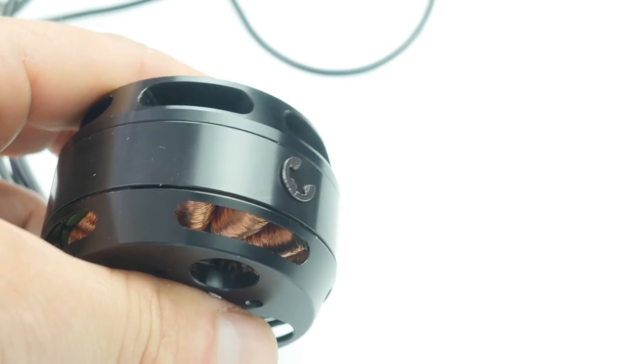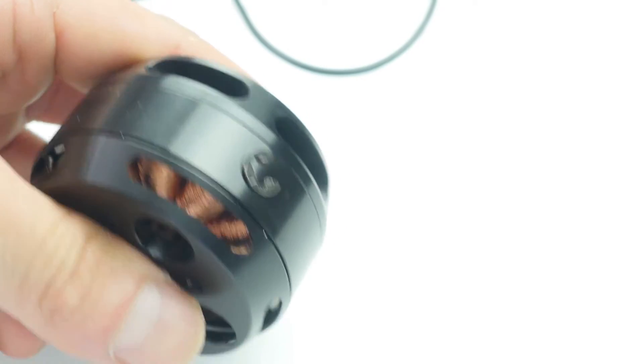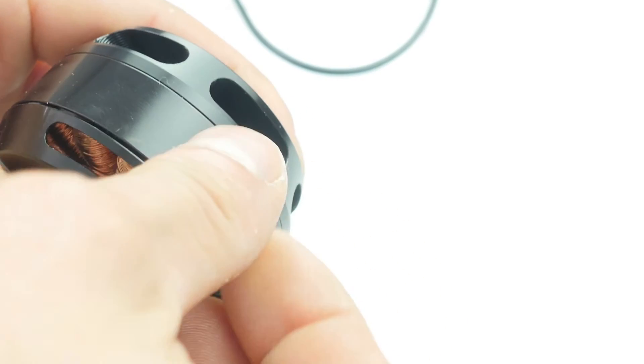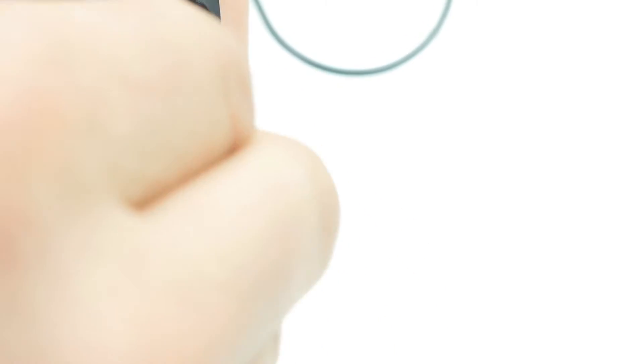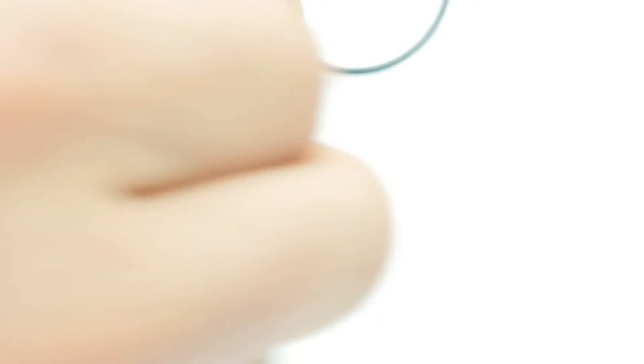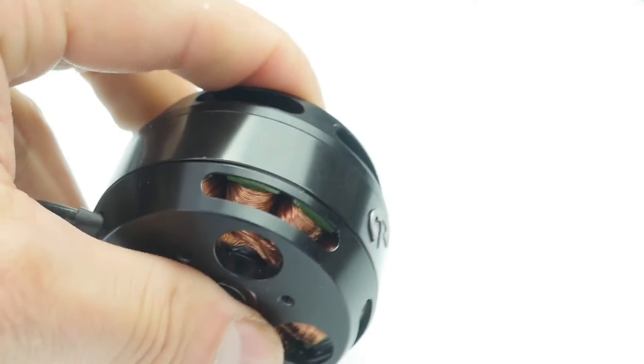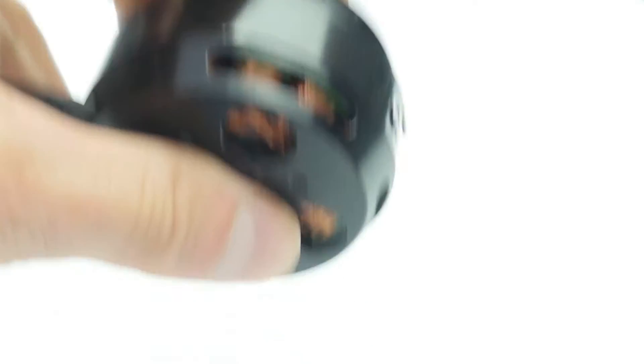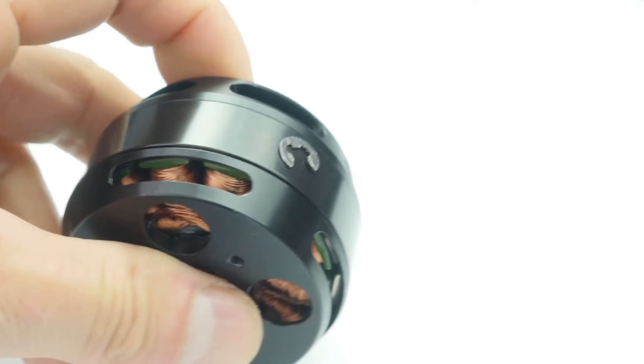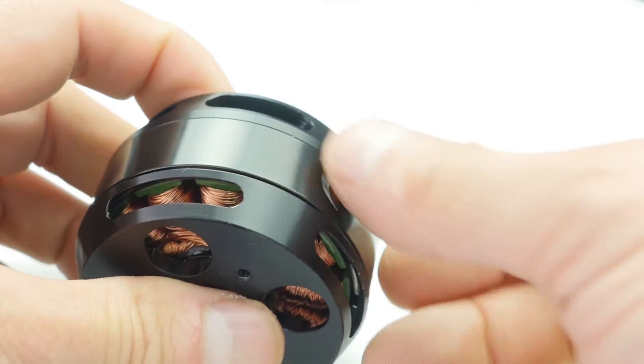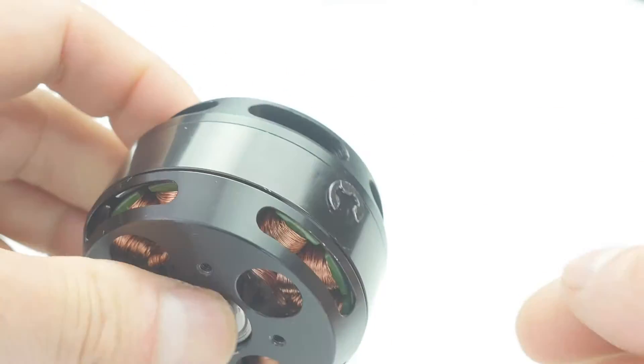The way in which the blue balancing epoxy is applied definitely leaves a lot to be desired. Magnetism that's lost through the outside of the end bell is called flux loss. This steel E-clip, which shouldn't stick at all, shows how much magnetism is lost through the outside of the U7. The U7 failed this test miserably.